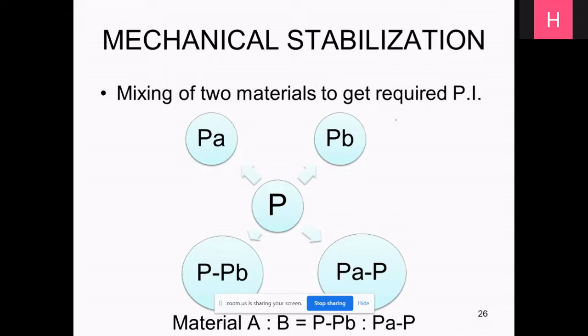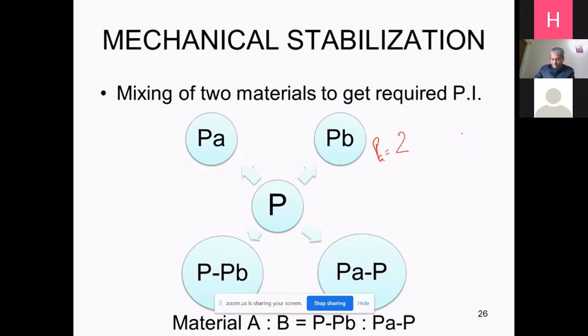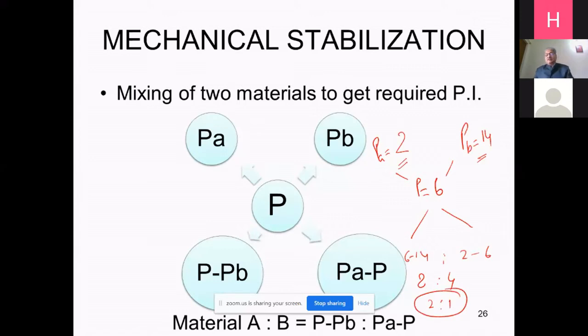So for example, suppose you have a material having PA equal to 2, PB equal to say 14, and you require the P to be 6. You require the material of PI 6, but you have 2 materials with you. One is having PI 2, another is having PI 14. So you have to mix them in such a manner that (PA minus P) ... that is, P minus PB, 6 minus 14, is to PA minus P, that is 2 minus 6. 8 is to 4, that is 2 is to 1. In this ratio, you have to mix the material. This was the CRRI method. And based on that, you can decide the mixing material.